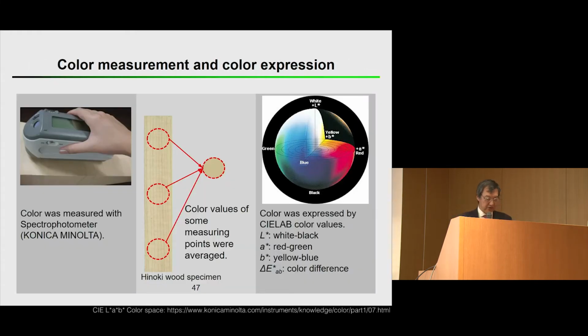So in order to check the color precisely, we can use the spectrophotometer and measure the color values such as lightness L*, white and black, a*, red and green, and b*, which is yellow and blue. Delta E is the color difference, which is actually calculated from these three elements, lightness, red, and yellow.